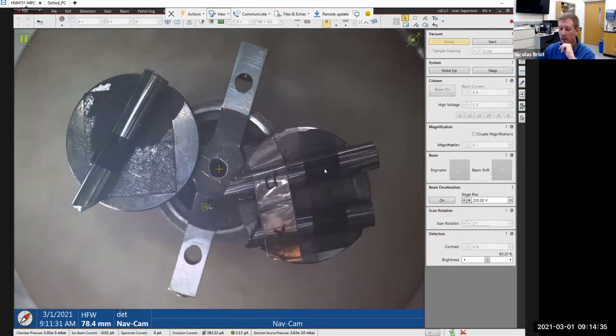So remember what we talked about last week about needing the sample to be conductive or somewhat conductive for electron microscopy, because we send electrons, they have to go somewhere. So glass is really not a friendly sample. So what I did is I used some conductive carbon paint here. And I also sputter coated some regions. I masked the center, but I sputter coated some regions with a gold palladium alloy. So I have maybe 10 or 15 nanometers of metallic coating that hopefully goes all around the sample and meets the graphite coating, so that when I image, hopefully the electrons can go to that film and escape the sample, so we don't have too much trouble. But this at the center is the sample without any coating. So if we do EDS on those, we're not going to have any gold palladium from the coating. Okay.